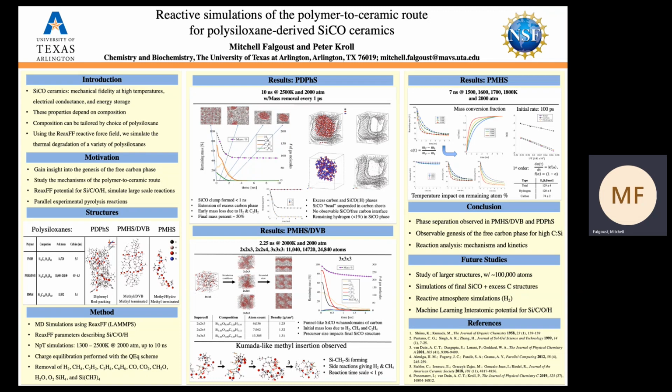So this is a Kumada-like process shown here on the bottom of the middle section, which is the methyl insertion between two silicon, which eventually lead to the silicon carbon tetrahedra, or the silicon carbide phases, which can nucleate in the middle of the SiCO phase.